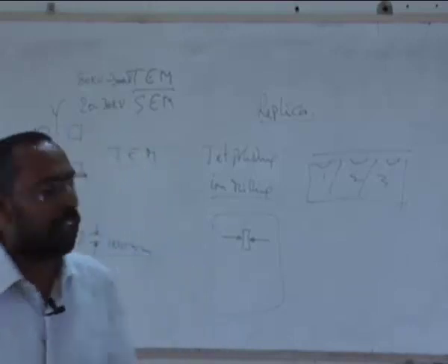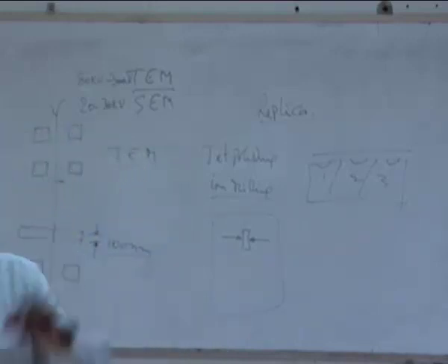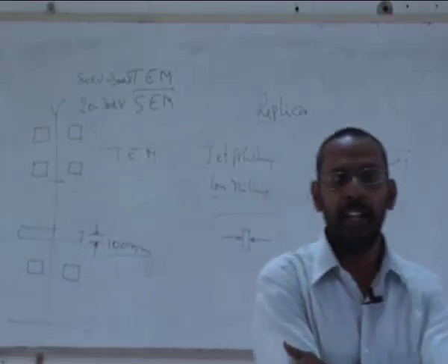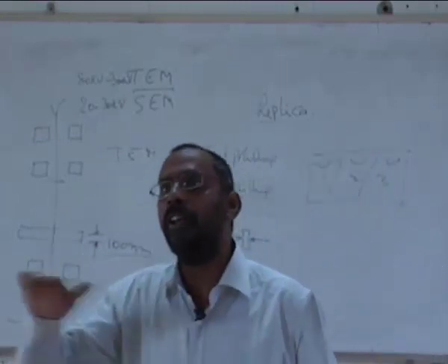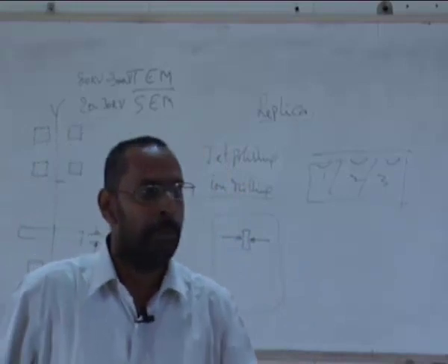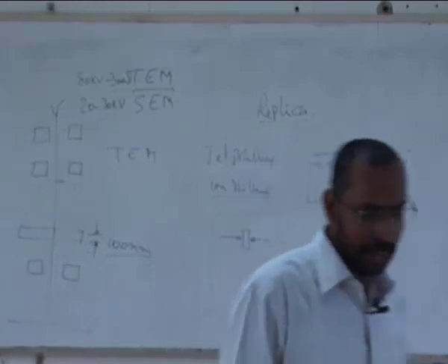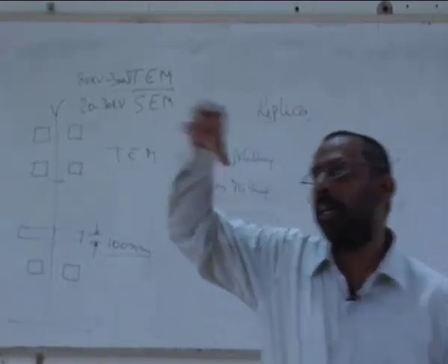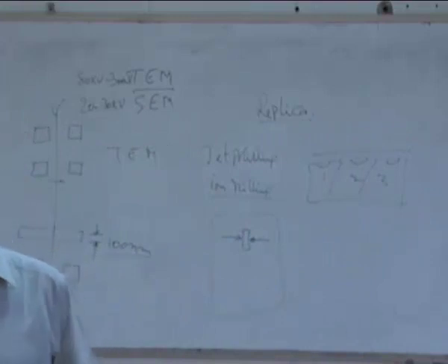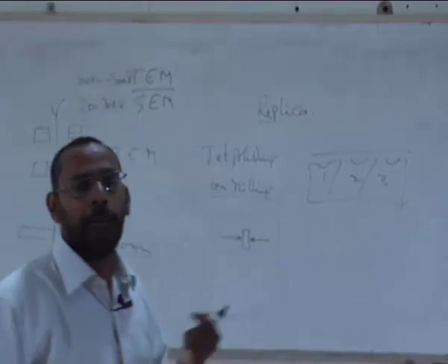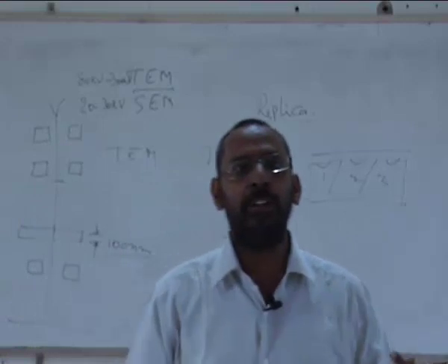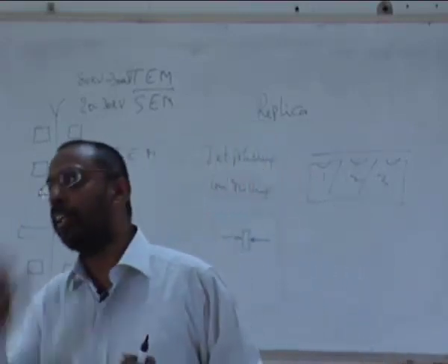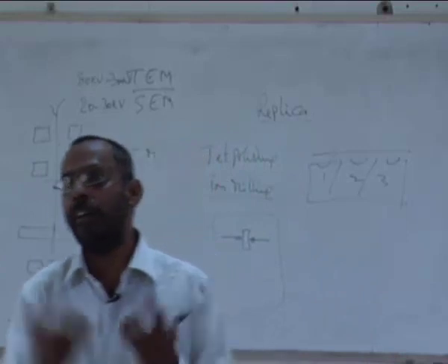and when you polish your surface, if you have some hard particles, which are inclusions, usually these hard particles are not polished easily when compared to your sample, because your sample is less hard than the particle. For example, if I have an aluminum alloy with some alumina inclusions, or a steel with some inclusions of either silica or some other inclusions which have been formed during the preparation of the steel, and the slag inclusions which are entrapped into your material, these are all oxides, so they are very hard when compared to the sample.